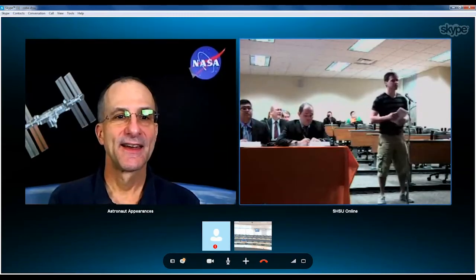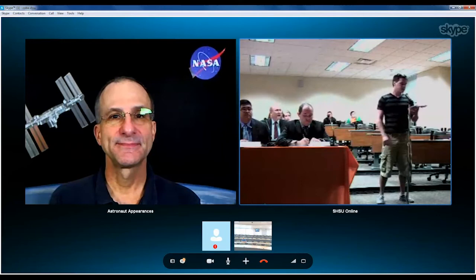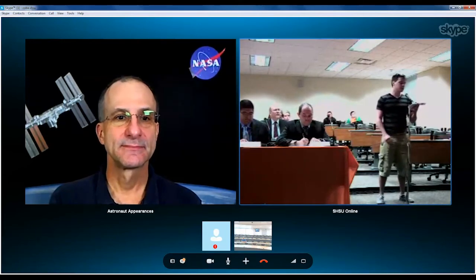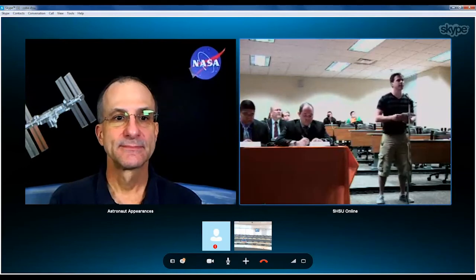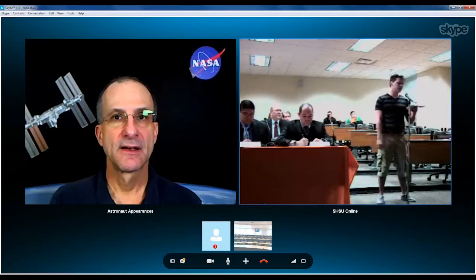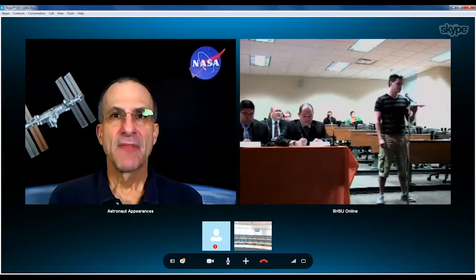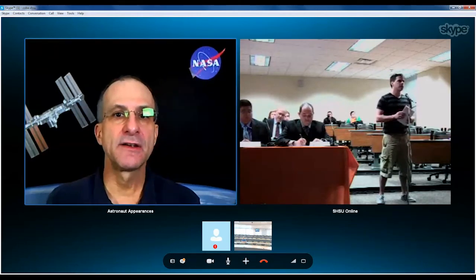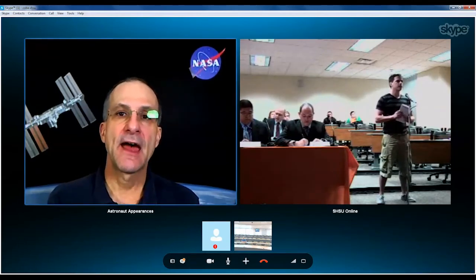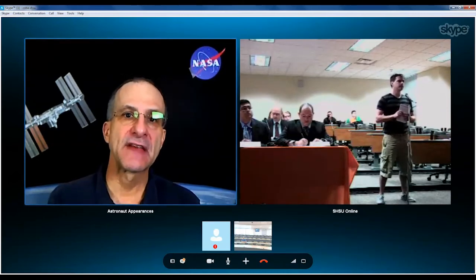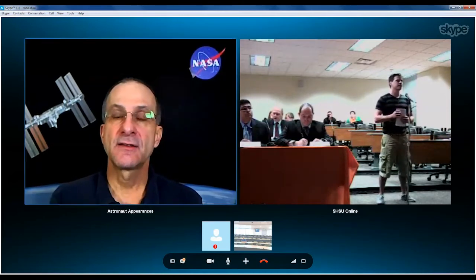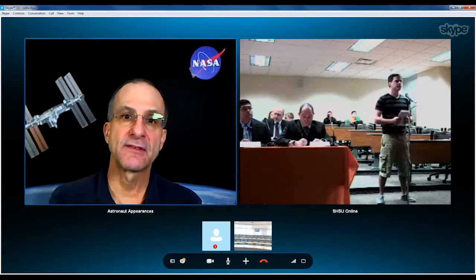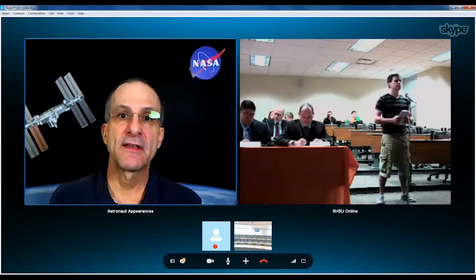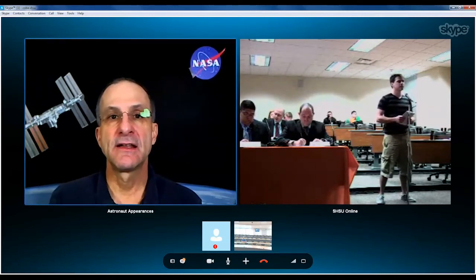Hi, Dr. Pettit. My name is Nathan. I'm a chemistry major here at Sam Houston. I had a couple of quick questions. You keep saying this compound sets on the leading edge of the space shuttle during re-entry into the atmosphere. What is the minimum temperature that this compound decomposes into glass at? Probably around 1,200 degrees centigrade, something like that. It starts to flow around 1,200 centigrade, and then it's stable up past 2,000 degrees centigrade. At least that's what it showed during the testing that we had in the vacuum chambers.